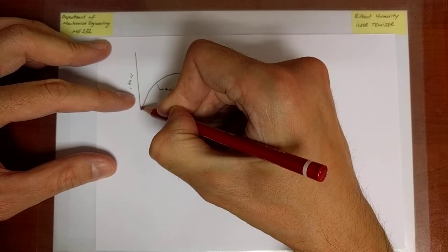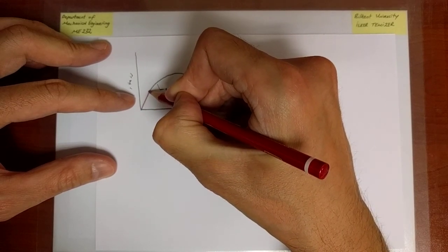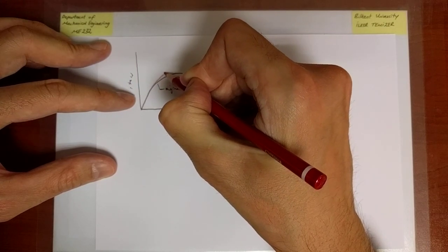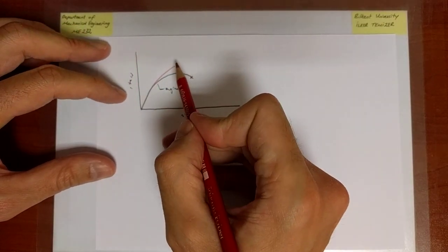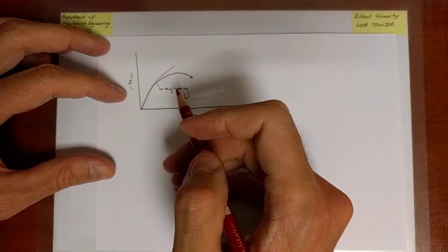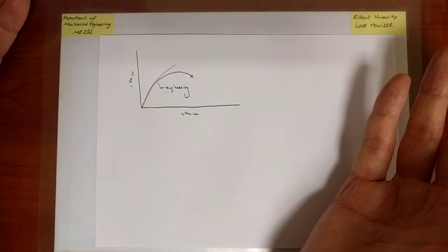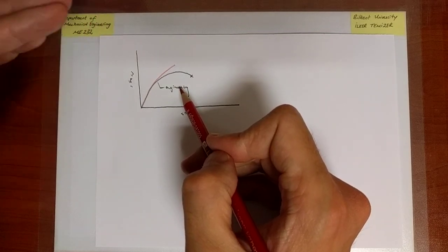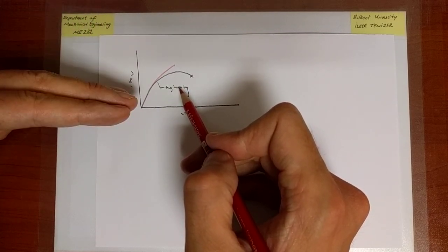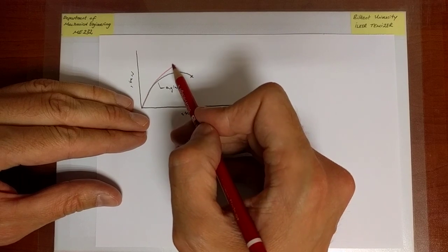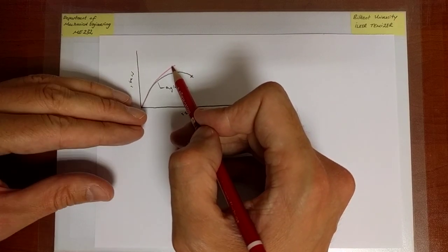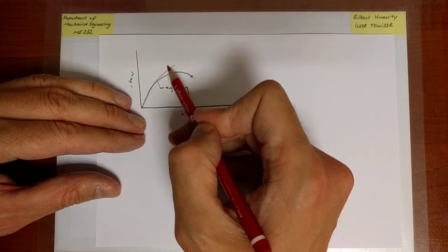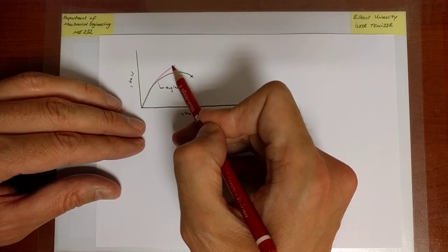Now, first of all, the stress is going to be larger. We can easily see that because the load at any stage of loading is given. For the engineering stress-strain curve, we divide the load by the undeformed area, whereas for the true stress curve, we divide the load by the deformed area, which is smaller, and therefore, as we said, the stress is larger. So the true stress-strain curve, the red curve, is going to be larger.